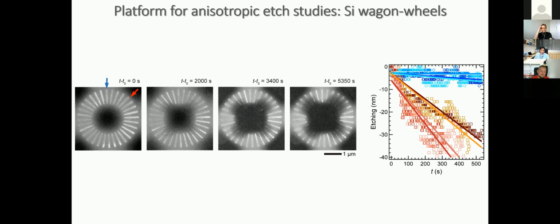And you see not all of them at the nanoscale etch very uniformly. In bulk, over time, when you do the etching in the bulk, you say, okay, my etch is 3 hours, sometimes it's 3.5 hours, and so on. But at the nanoscale, because you're etching a very small amount, you can be very sensitive to these discrepancies in the times, and then certain directions might etch a little bit at a different rate.